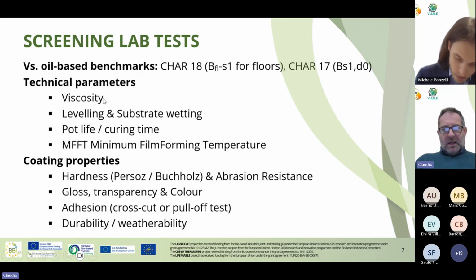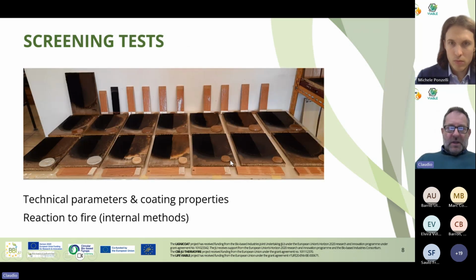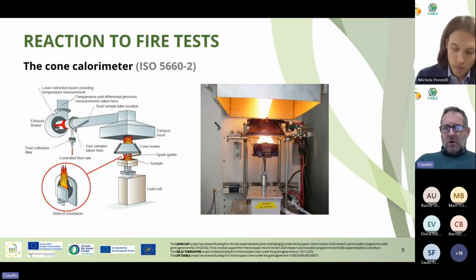of parameters. As I mentioned before, we need to have all these properties to have something that we can consider a good coating material. So we made quite a number of specimens at the beginning for physical testing, then for a simple internal method for reaction to fire testing to appreciate whether we were able to protect the substrate and to which extent, and to observe whether we had charring to some extent or no charring or whatever. And the results, the better products from these screening tests were brought to the cone calorimeter.